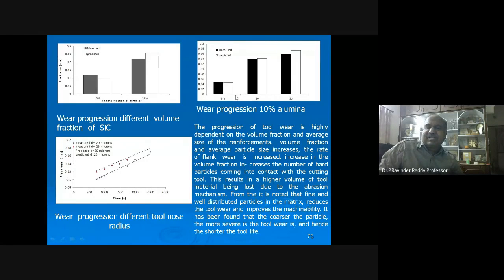If you see here, we have progression at 10% alumina. So the measured is black and white is predicted. You can observe here at volume fraction 9.5, 20, 25. Again, it is increasing. The level of increase and all, also you can see the magnitudes. We see the same flank wear rate, you can also see, measuring at a different micron level. So we have 20, 25, again 20, 25, both measured and predicted.